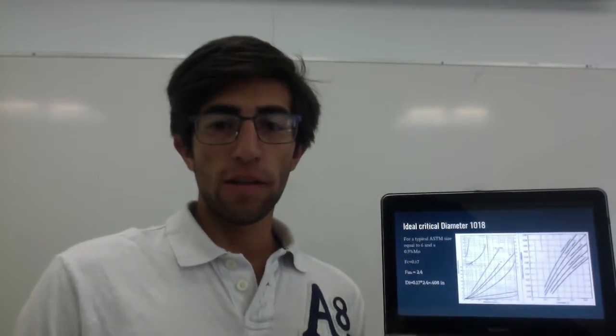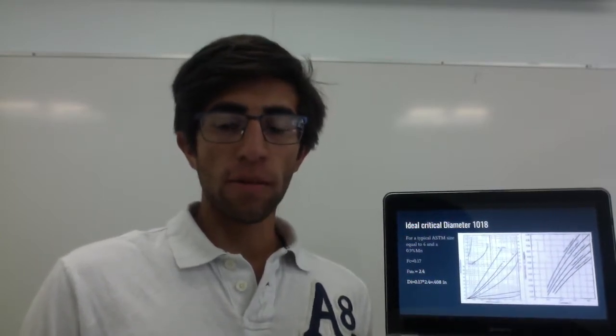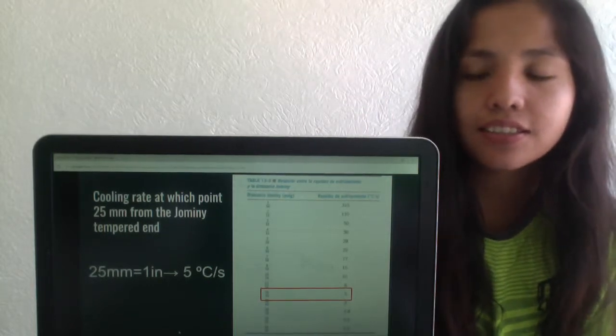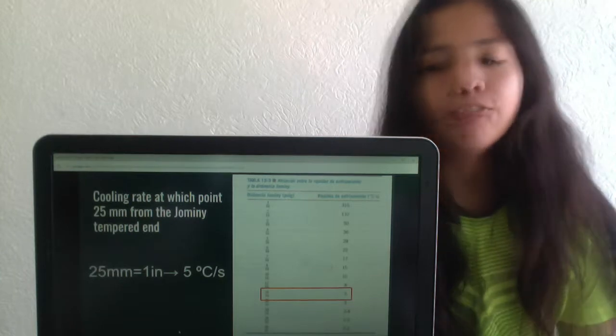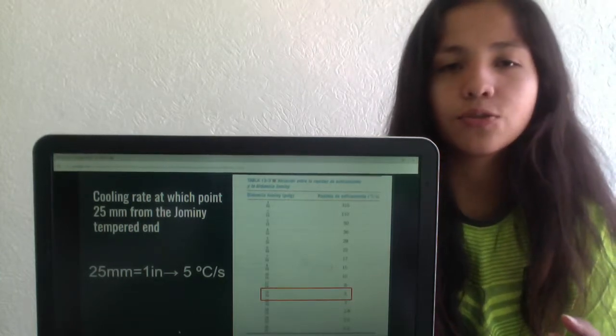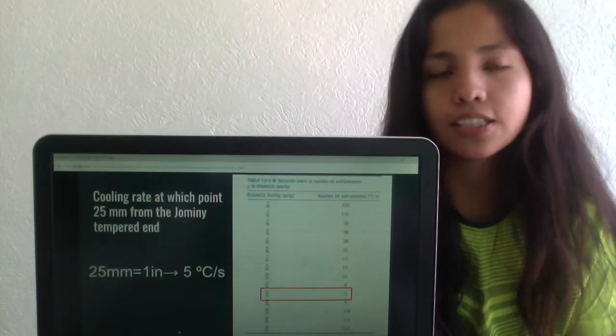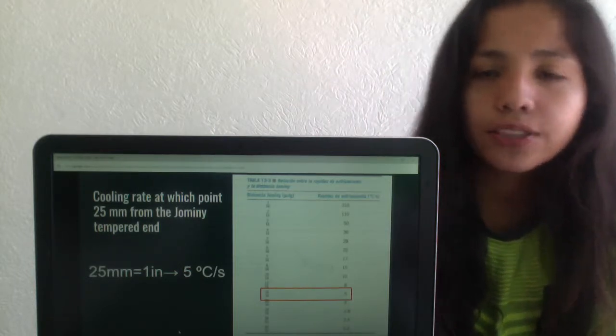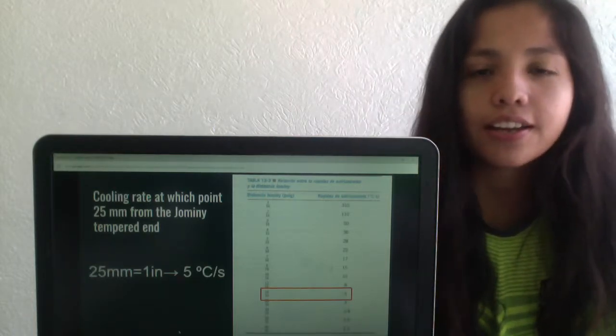For a typical ASTM grain size of 6 for the steel 1018 and 0.9% of manganese, we have the constant for carbon that is 0.17 and the constant for manganese that is 2.4. Thus, the ideal critical diameter is 0.408. Thus, that means that it has poor hardenability, as we already said. And this table correlates the Jominy distance and the cooling rate. For example, at a point 25 millimeters from the Jominy quenched end, which is 1 inch, the cooling rate is 5 degrees Celsius per second.